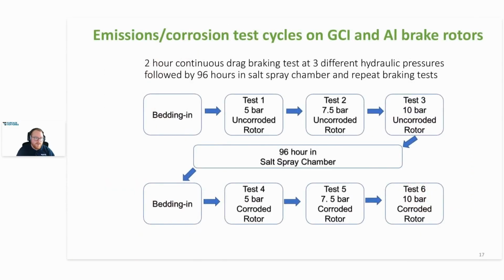Okay, so after bedding in, all three rotors were subjected to repeated drag braking testing at a speed of 150 RPM and hydraulic pressures of 5, 7.5, and 10 bar. Each test lasted for around 120 minutes and was repeated 3 times to check for consistency. Then, after 96 hours in the salt spray chamber, the whole sequence was repeated again for the, at that point, corroded rotors.